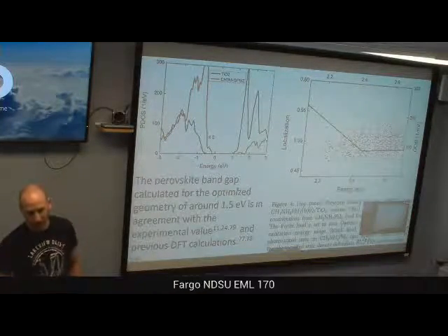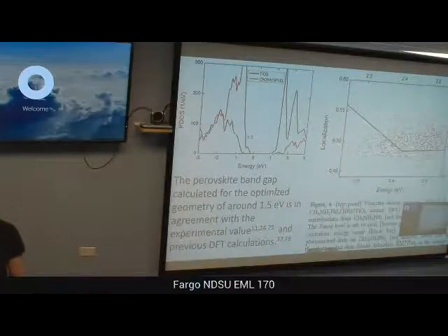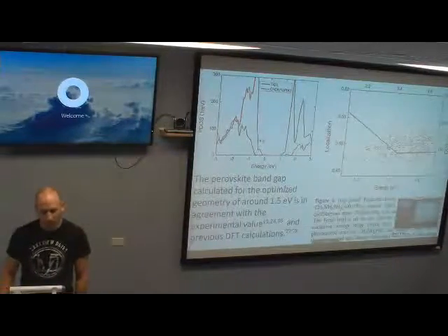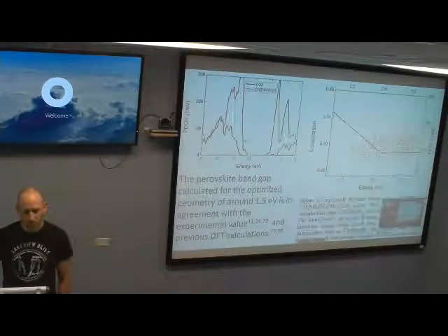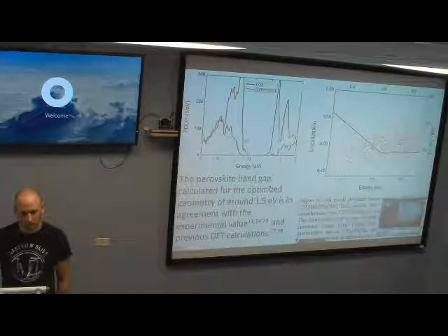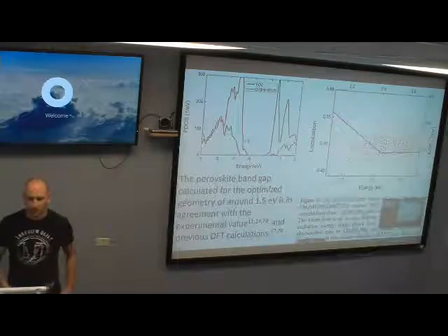This is if you want to excite the perovskite, right? So then you can go from HOMO or close to HOMO, not to LUMO, because LUMO would be completely a charge transfer state, which probably is not optically active. Right. So you need to go a little bit above, and that's why the 0.25 above is probably where you have contribution of the perovskite.